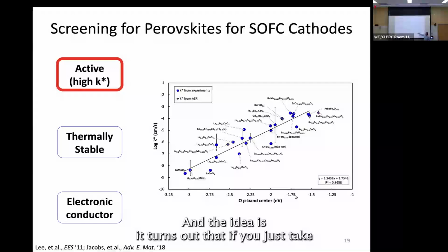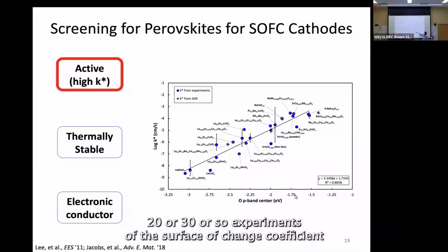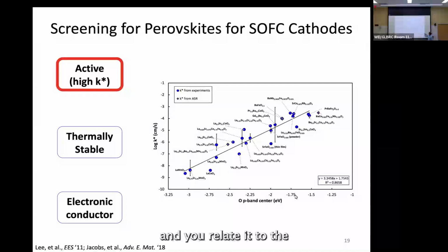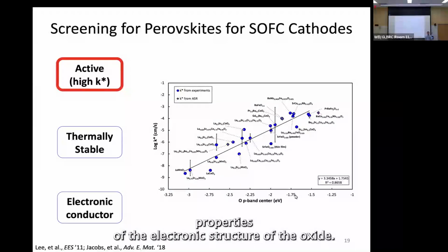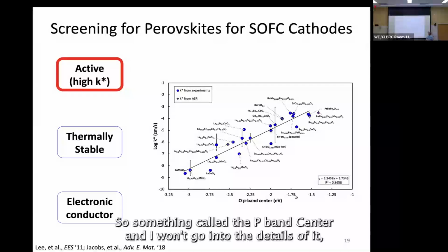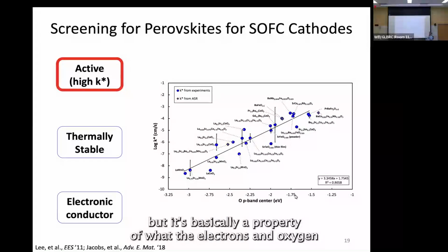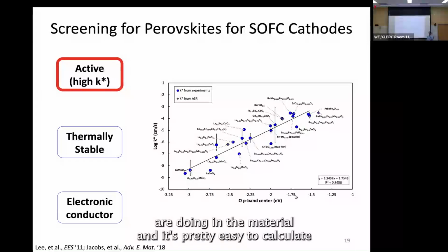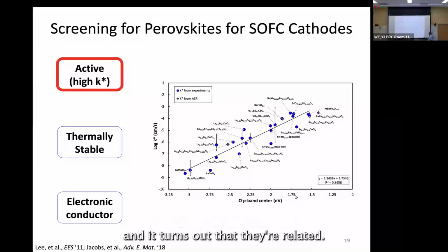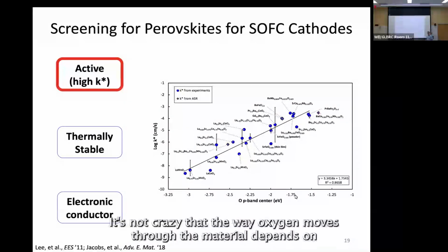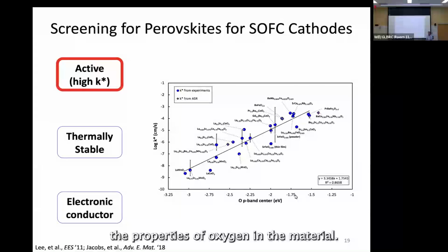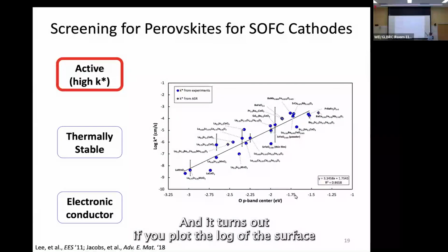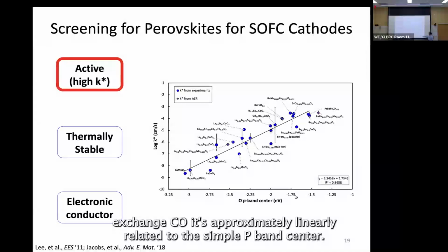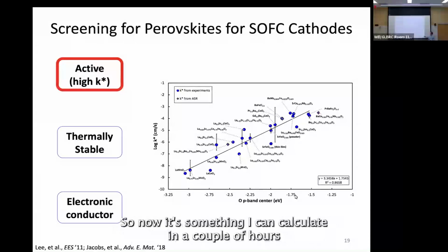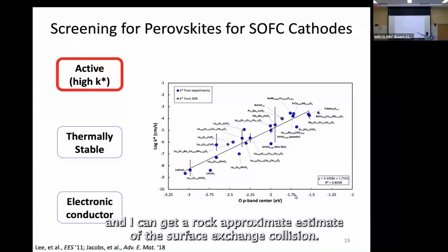The idea is, it turns out that if you just take 20 or 30 or so experiments of the surface exchange coefficient, and you relate it to a property of the electronic structure of the oxide, something called the p-band center, and I won't go into the details of it, but it's basically a property of what the electrons on oxygen are doing in the material. And it's pretty easy to calculate. And it turns out that they're related, and this isn't crazy. It's not crazy that the way oxygen moves through the material depends on the properties of oxygen in the material. And it turns out, if you plot the log of the surface exchange coefficient, it's approximately linearly related to this simple p-band center. So now I have something I can calculate in a couple hours, and I can get an approximate estimate of the surface exchange coefficient.